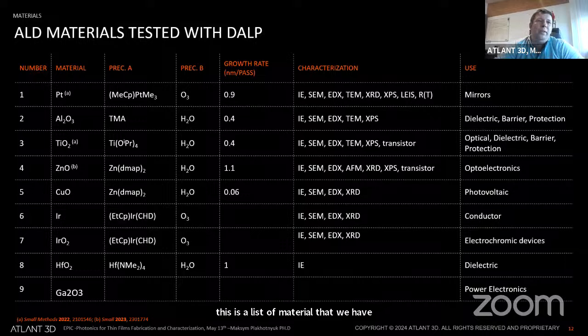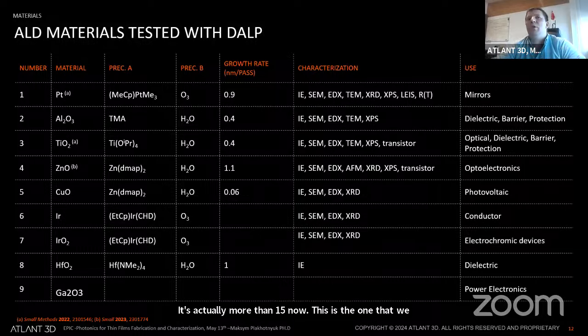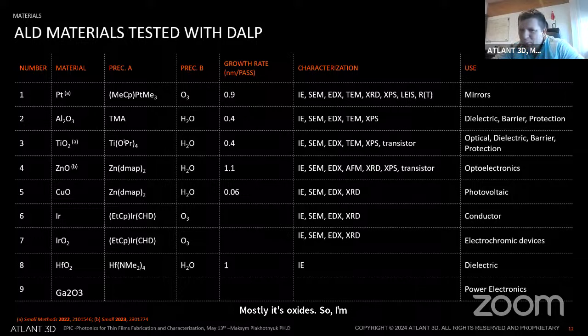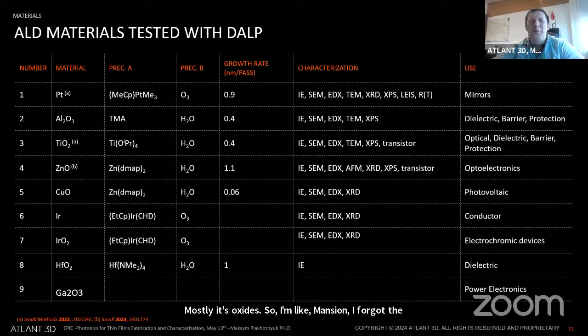So this is a list of materials that we have validated. It's actually more than 15 now. This is the one that we have confidence that we can reproduce. A lot of other materials we are testing still, so I'm not advertising them. Mostly it's oxides. IMEC mentioned, I forgot who was that, sorry. Don't want to be impolite. So aluminum oxide, titanium oxide, zinc oxide, iridium, hafnium oxide. We recently demonstrated gallium oxide and planning for niobium oxide also within the next month.